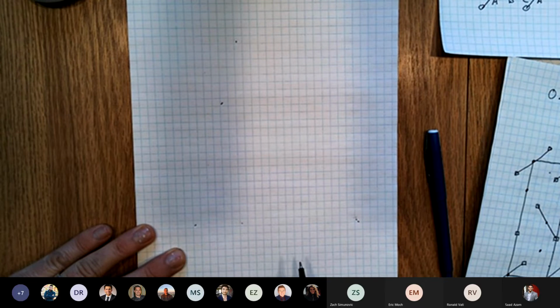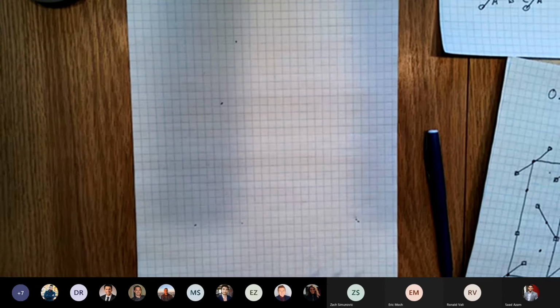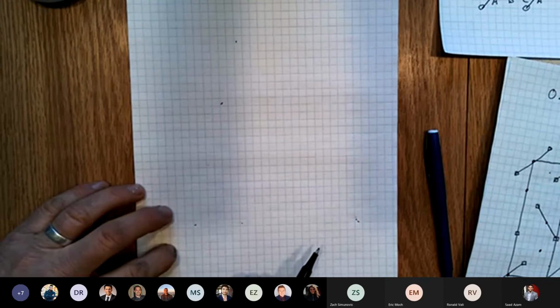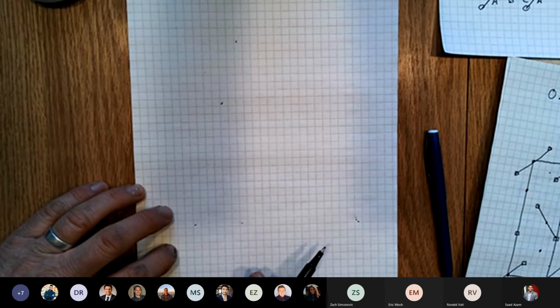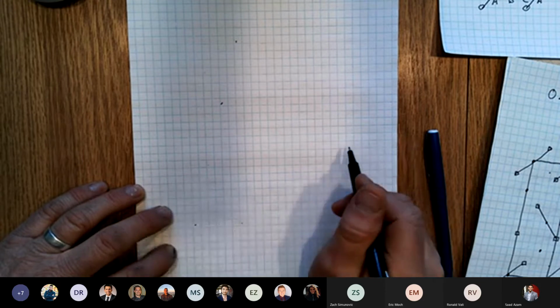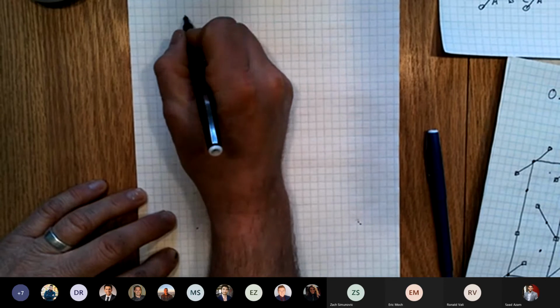And you can make this alternative structure for NMC or NCA or anything you want. But it's harder to make. It's more expensive to make. And if its properties were significantly better than O3, people might do it. But the properties are not better, so people don't do it. But no one knew this at the beginning. So it's important to understand what this is.